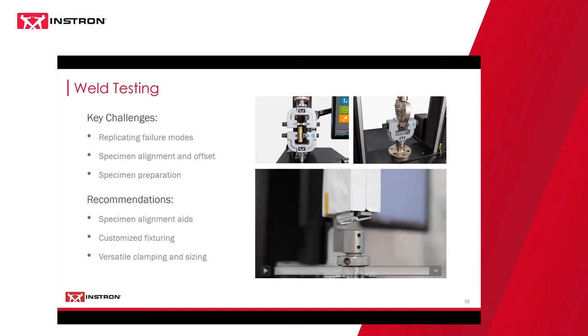Other things we have here: the picture in the top left shows an example of a cylindrical cell. This one was measuring a tab to cap weld. It utilized custom jaw faces, what we call shoulder jaw faces, that were able to hold the cap at an offset so that you were breaking the weld along the axial center of the load string. We did find that some tests like this were very critical to having proper alignment in the center of a load string versus testing at an offset; the offset proved to have much less repeatable results.